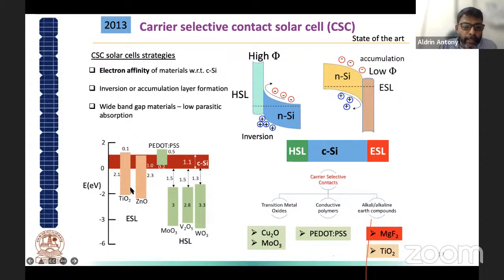So you could see this material, titanium dioxide, has a conduction band or electron affinity level that is almost balancing with regard to crystalline silicon. Crystalline silicon has an electron affinity of 4.05, and titanium dioxide has an electron affinity of 3.95.